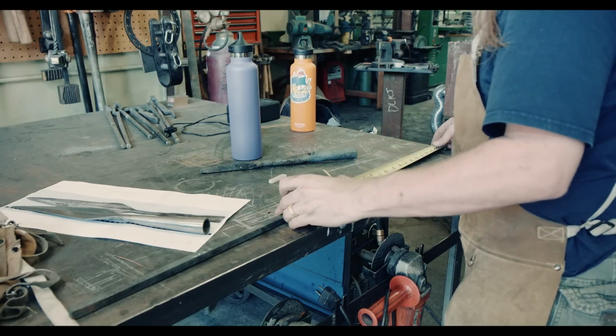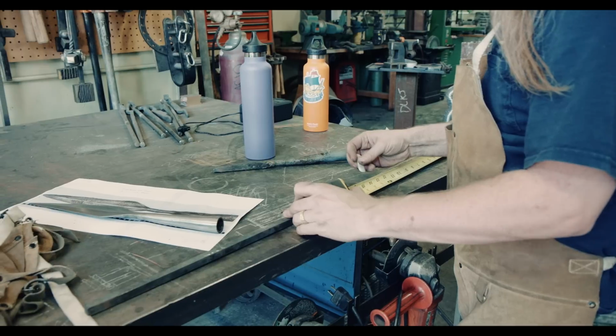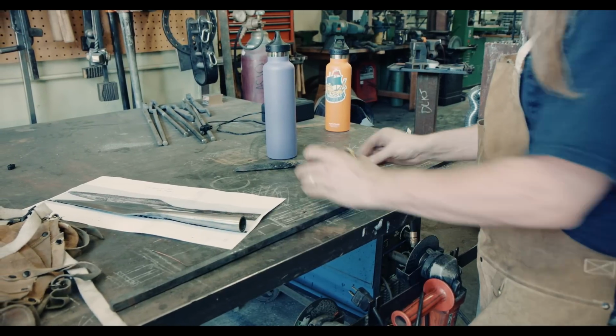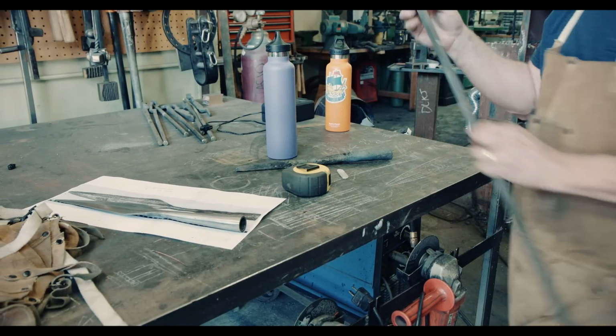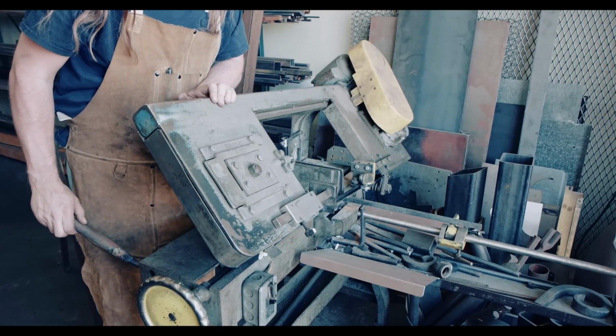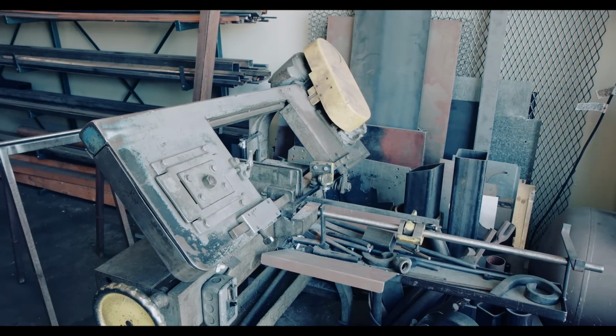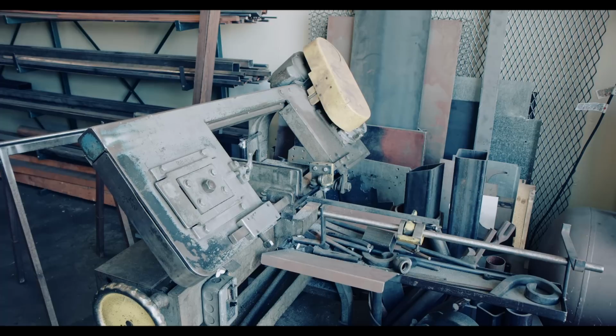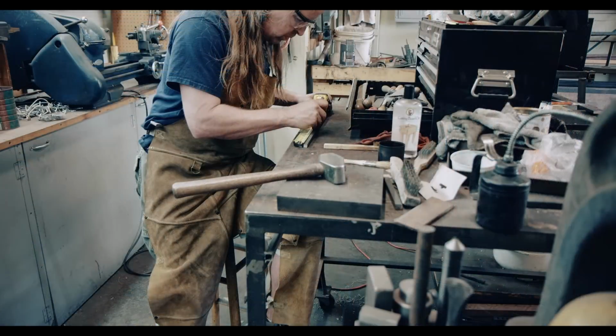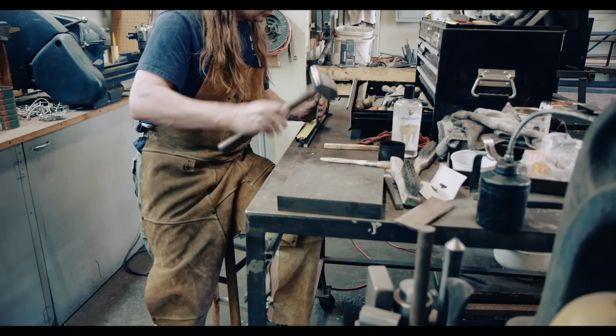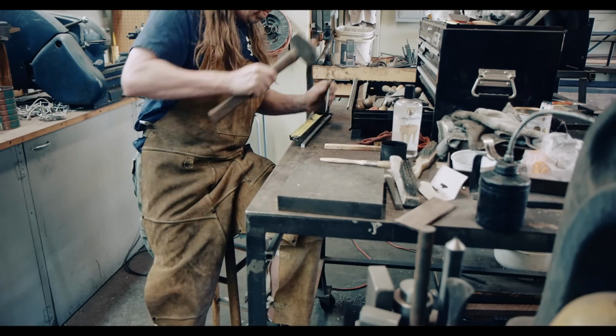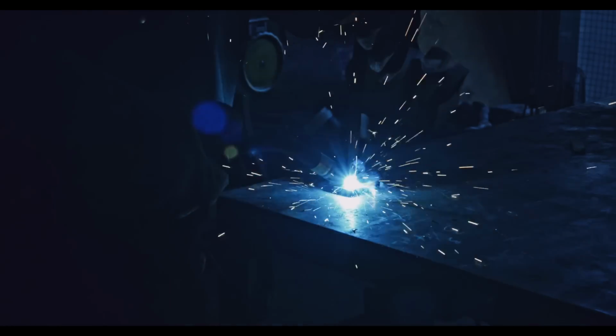In the pictures you saw earlier, you may have noticed that the twisted patterns on the spearhead came from one bar with different twist directions and a hairpin weld. Before we can twist, we need to prepare the bars, which starts by cutting them to the right length. The first step is to weld on 2 supports for my twisting jig, and slow motion makes that look almost magical.